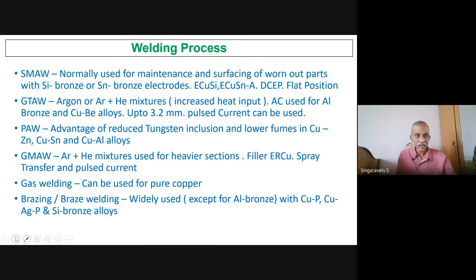Coming to the process side, SMAW is normally used for maintenance surfacing of worn-out parts. Electrodes are available, ECUSI, ECUSN, and so on. Use DCEP. As I said earlier, do flat position welding. In the case of TIG, argon or argon-helium mixtures are used with increased heat input. AC is used for aluminum bronze and copper beryllium alloys up to 3.2 mm. Pulsed current can also be used in TIG welding.